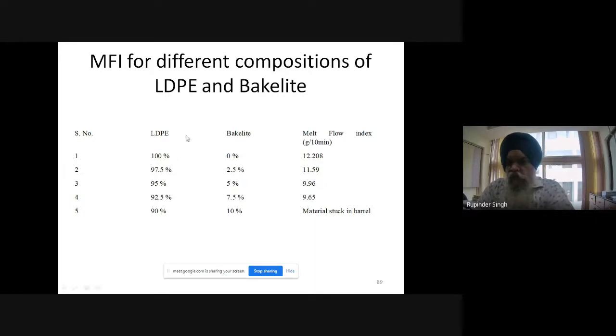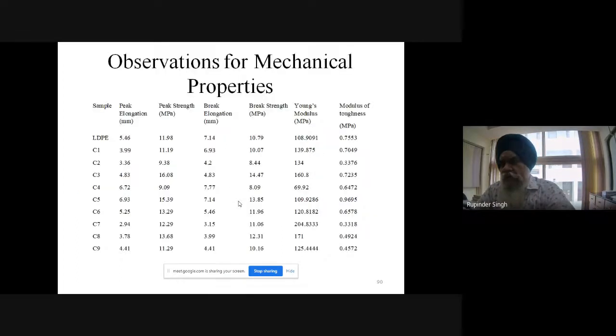So to make this type of material, we started initially with 100% thermoplastic, and we got an MFI of 12.2. Then we went on reinforcing the bakelite by weight percentage. So we were able to have this proportion up to 7.5%, and the MFI was 9.65. But what we observed, with the higher proportion of the bakelite, even at 7.5%, the material was so brittle that its spoolability was compromised, so we were not able to print that part, right?